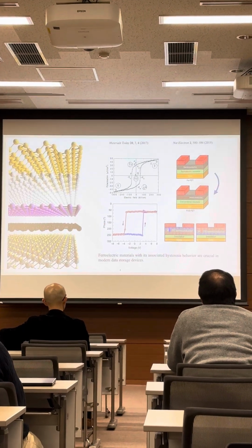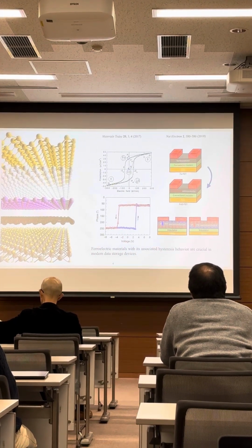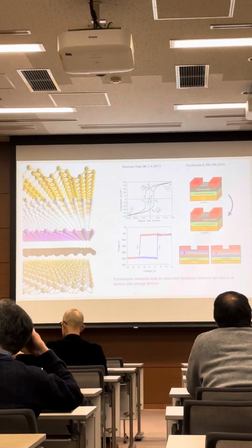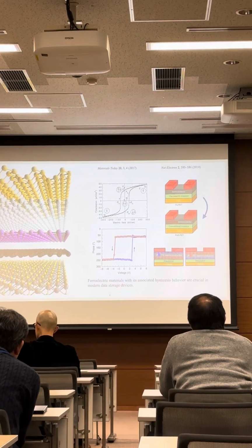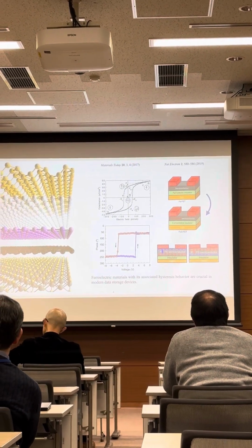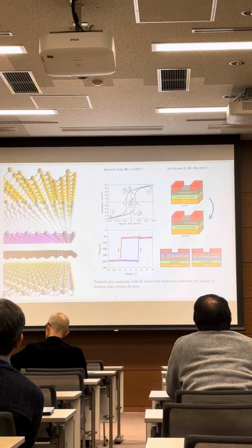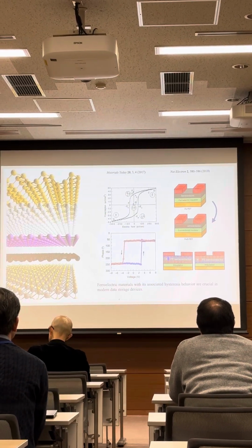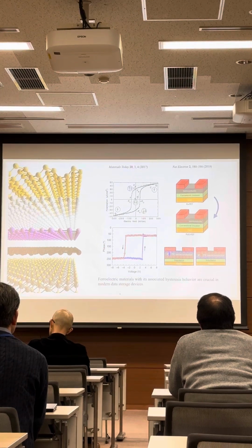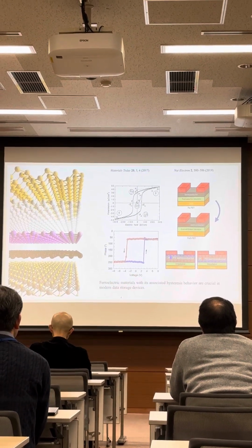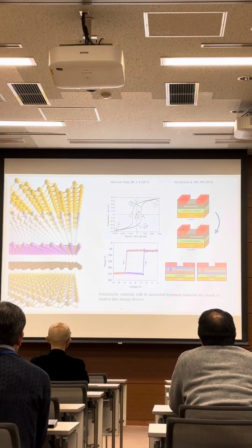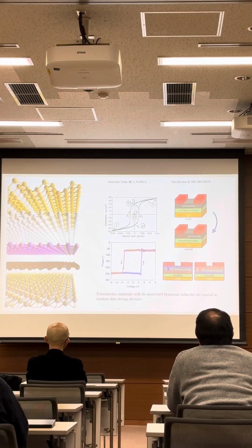In the FeFET, the ferroelectric is employed as a gate insulator, so that the channel conductance is used to detect the polarization state in the gate, so that the data reading operation of this FET is non-destructive. So ferroelectric FETs are a promising memory technology due to the fast switching speed of these ferroelectric materials, non-destructive readouts, and simple structures for high-density integration.